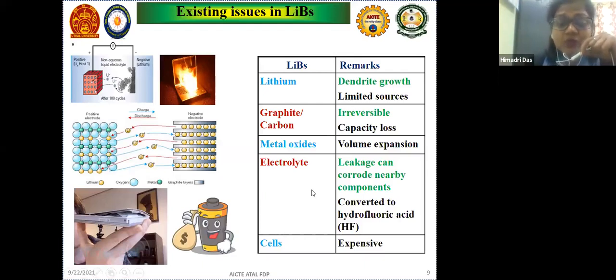Apart from that, when we use an anode material like metal oxides or other anode materials, there is also the effect of volume expansion, which also affects the charge discharge of the batteries. As well as, the electrolytes face problems like leakage or corrosion, and sometimes there are other side reactions which degrade the quality of the battery. That's why, apart from all these cathode, anode and electrolyte problems, there is also a drawback that the lithium ion battery is quite expensive.